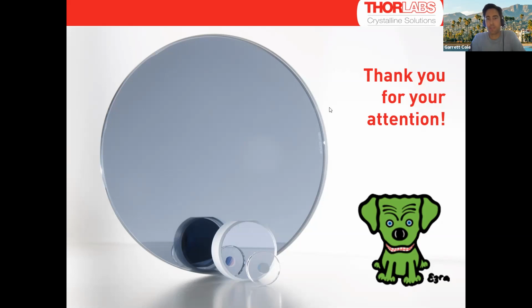Next question: how long does it take to grow a crystalline coating? For the crystal growth, about a micron an hour is a good rule of thumb. Our typical near IR HR coatings are about 5 microns thick, so call it 5 hours of deposition, whereas a mid IR coating might be 15 to 20 microns thick. It's still less than 24 hours, so you're depositing over 15 to 20 hours roughly for one of these thicker coatings. So it's not a slow process.